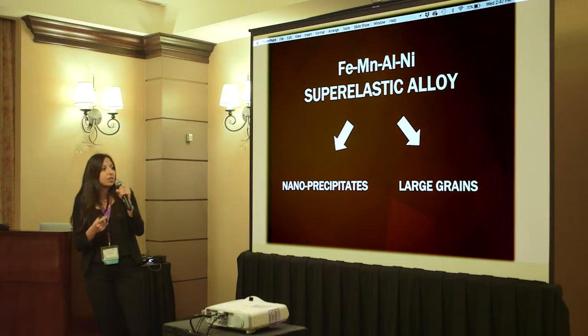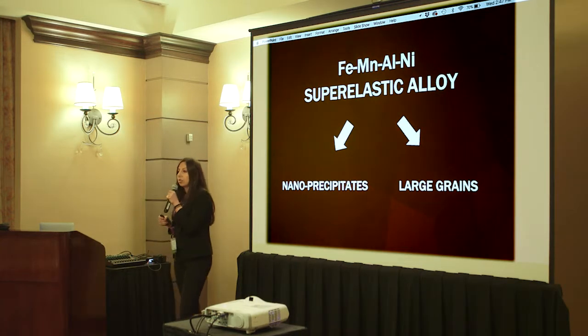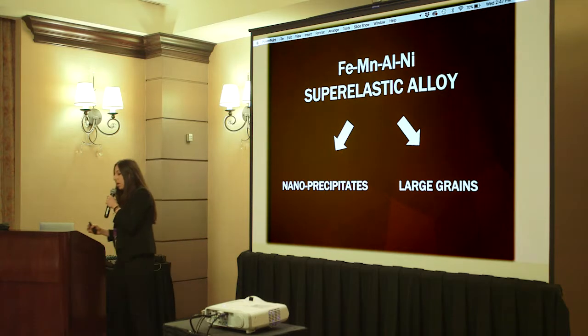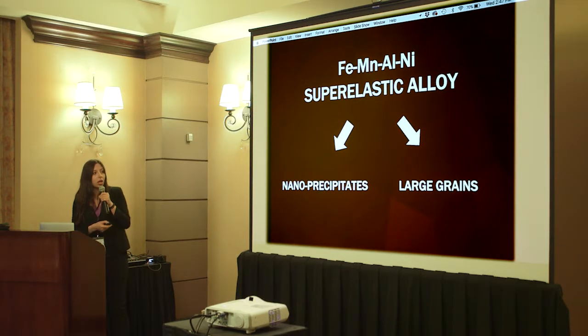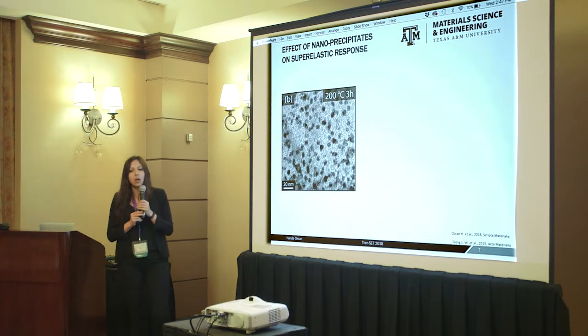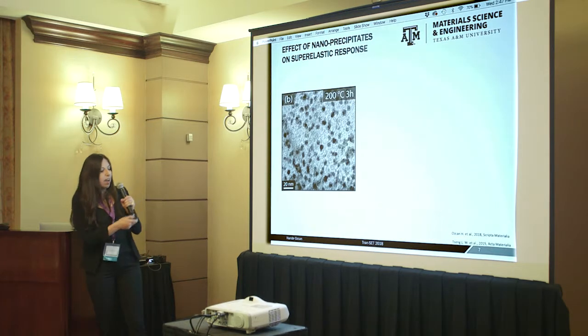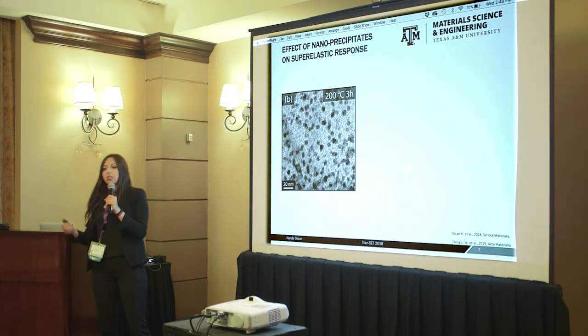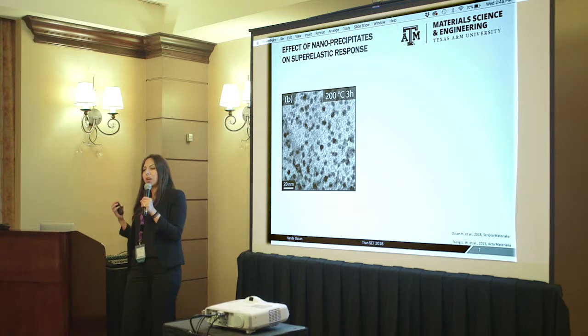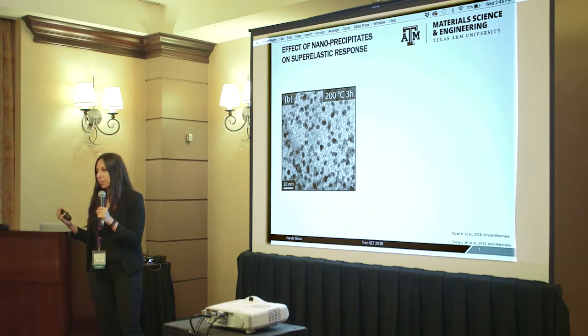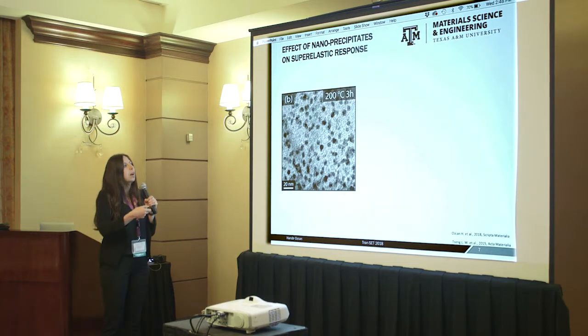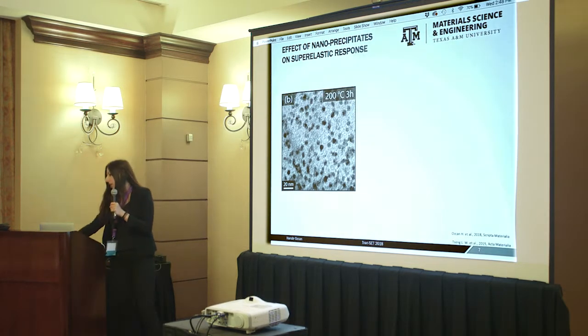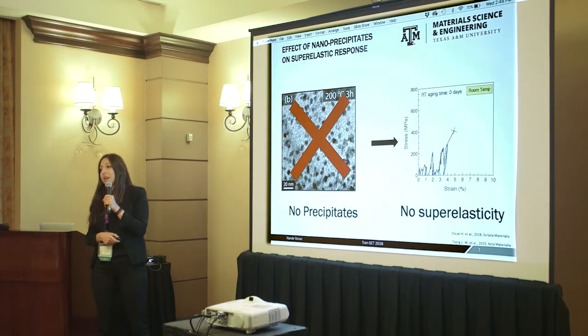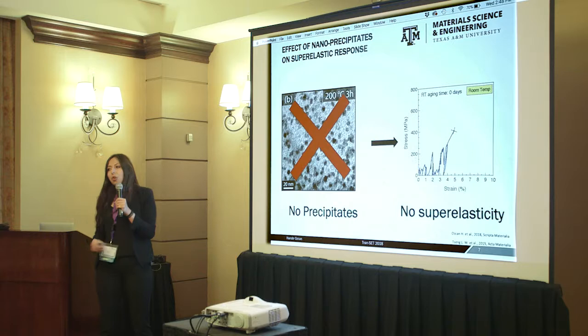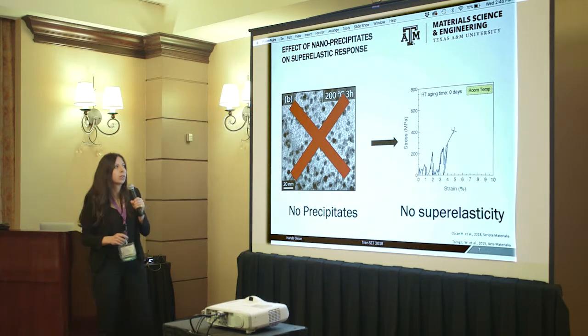Okay, how do these materials work? There are two things needed to get a good superelastic response out of this iron manganese aluminum nickel superelastic alloy. These are nanoprecipitates and large grains. What we need in this material is to have these nanoprecipitates. You can think of it as trying to make a nanocomposite material. You do some heat treatments and you induce these precipitates, and you can see that if you don't have any precipitates in the microstructure, you get no superelasticity. So this material doesn't work.